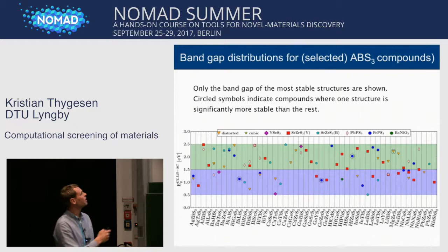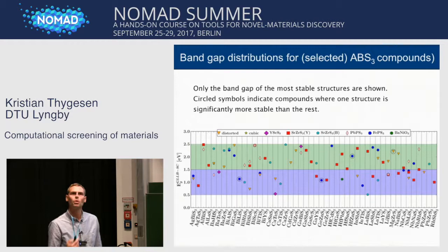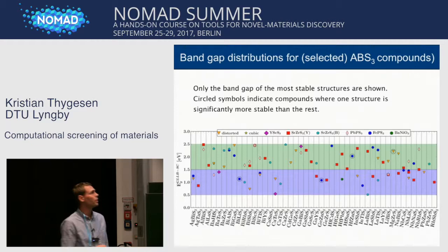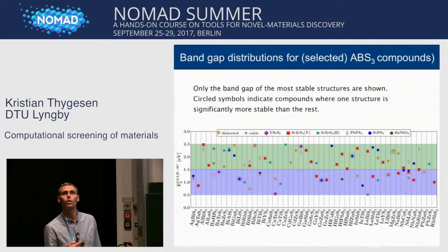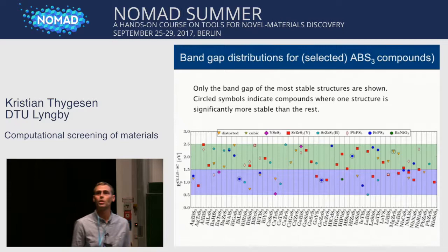So for example, here is silver tantalum sulfide. You can see there is only one material here. In this structure up here, you can see that has a band gap of 0.7. So that's something that could be interesting for photovoltaics with a single semiconductor absorber, so we keep that. So the blue window down here are materials that would be interesting for single junction photovoltaics, and the green up here is large band gap materials for tandem cells, okay, which is our main interest.